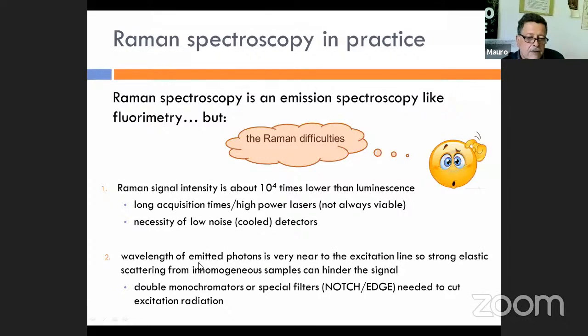Another shortcoming of Raman is that the wavelength of emitted photons is very near to the elastic line. This is because the distance between the Raman line and the excitation line is equal to the vibrational frequencies, which is very small in comparison to the excitation line. So we need special filtering to remove the elastic line, otherwise the noise associated with the elastic line will cover the Raman signal.